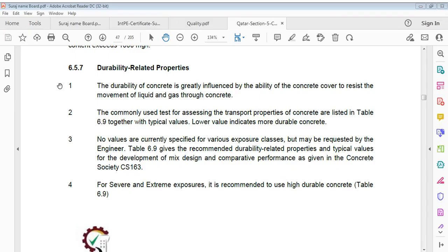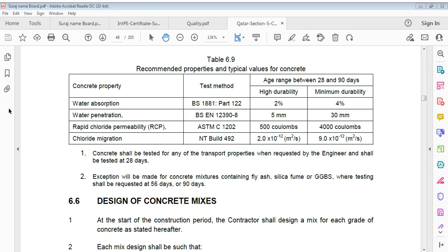Now for severe and extreme, the columns are test method, then high durability and minimum durability. First item is water absorption: 2% in high durability and 4% in minimum durability. Water penetration is 5 mm in high durability and 30 mm in minimum durability. Rapid chloride permeability, RCP, is 500 coulombs only in high durability, while up to 4,000 coulombs minimum.